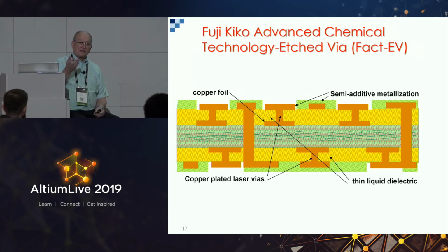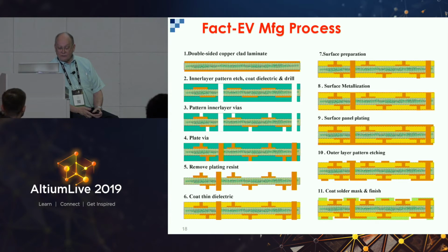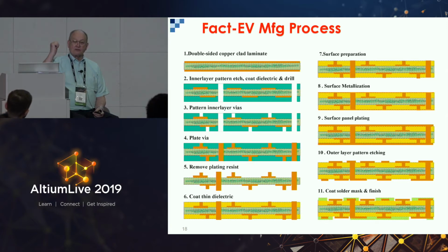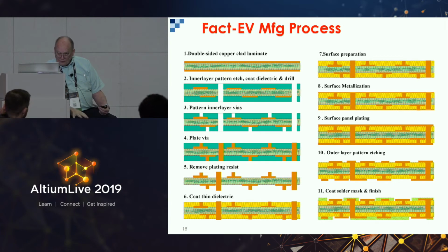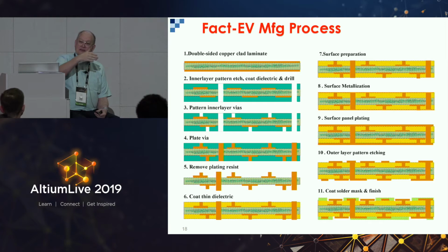The advantage of a liquid dielectric is it's much lower cost, and you have infinite thickness variation. So you can perfectly match impedances to your line width because you don't have to buy laminate cores. You use a liquid coating and then cure it, make it any thickness you want to match the impedance level without wasting material, kind of thing. So a FACT EV manufacturing process starts with a double-sided copper clad, because that's the power distribution layers. And then they build up the dielectric and then electroplate the vias, but then use a liquid dielectric.